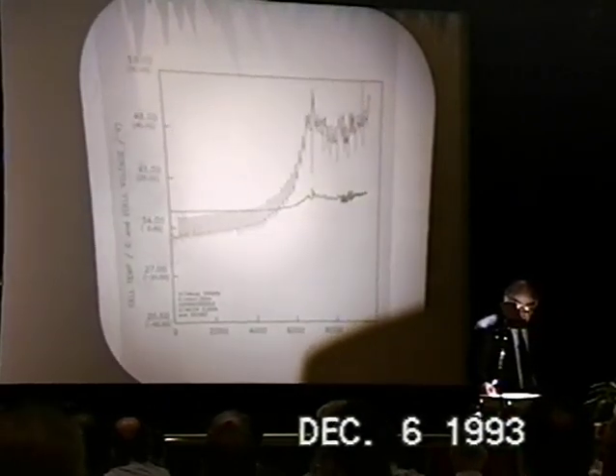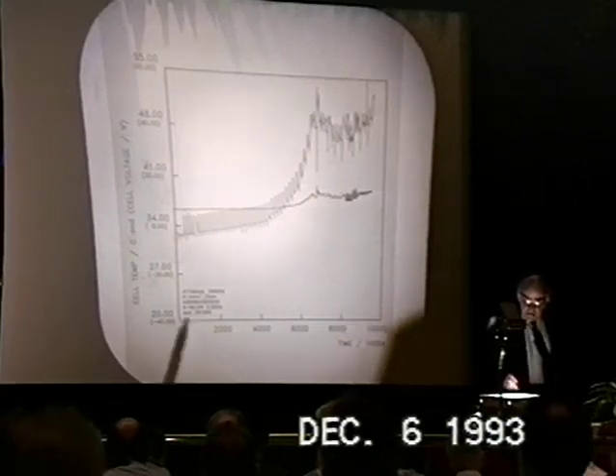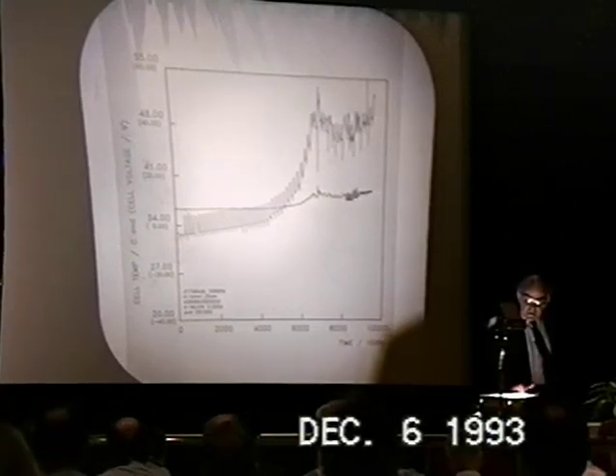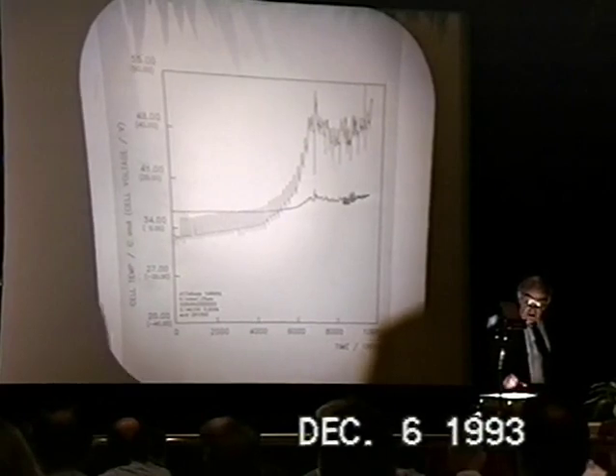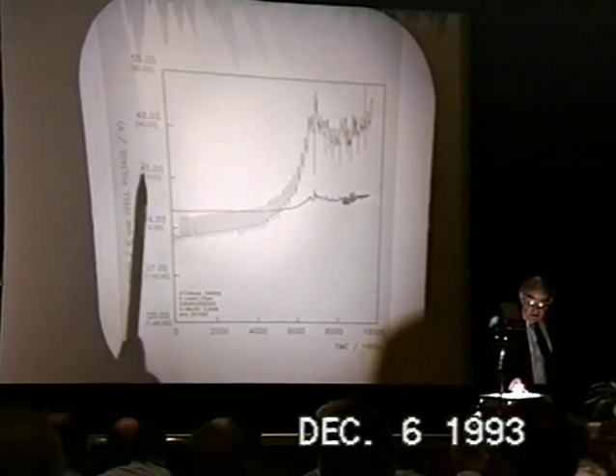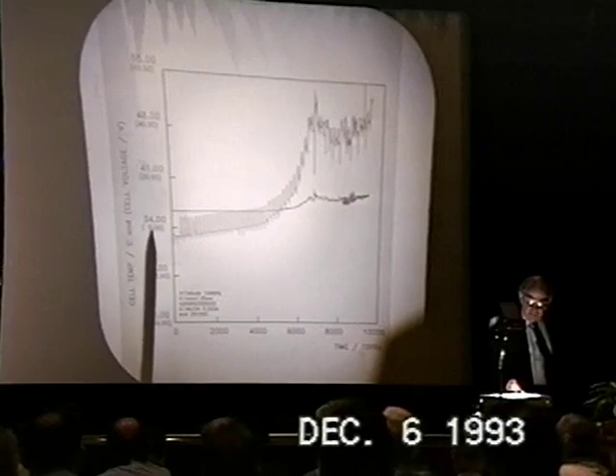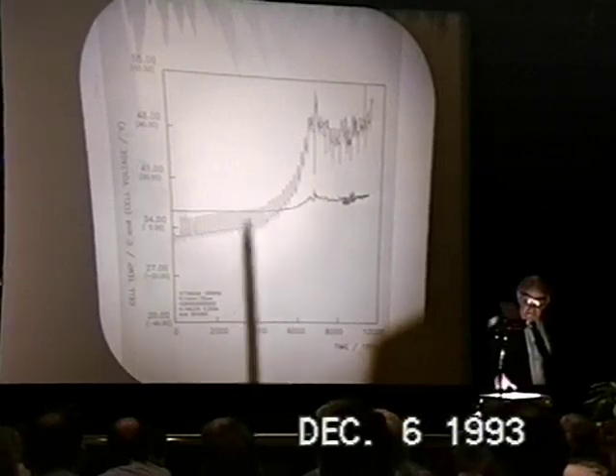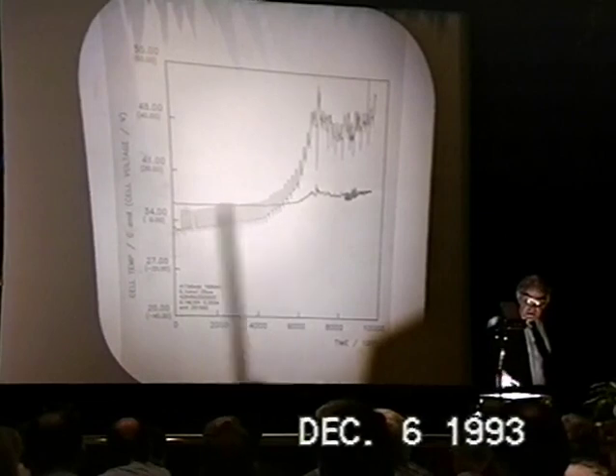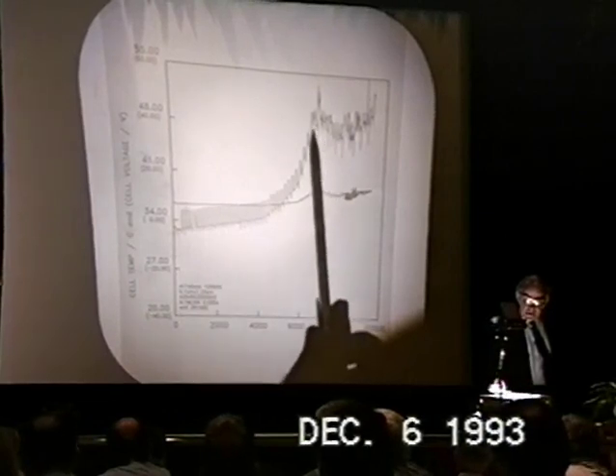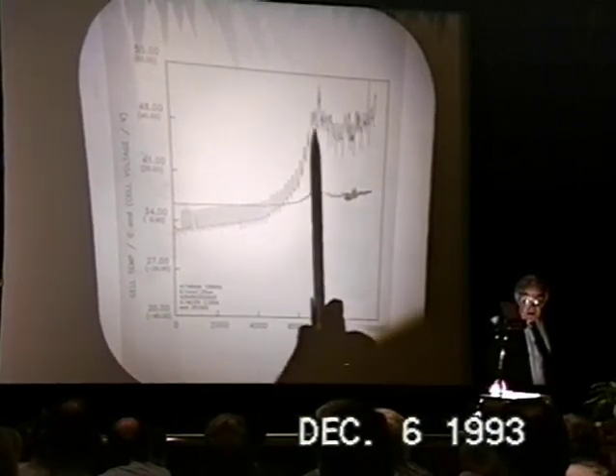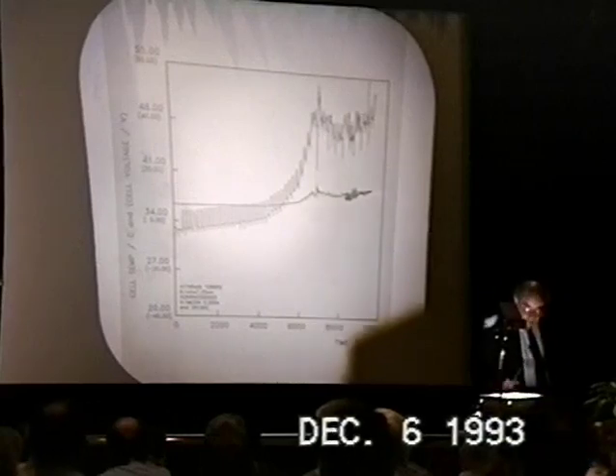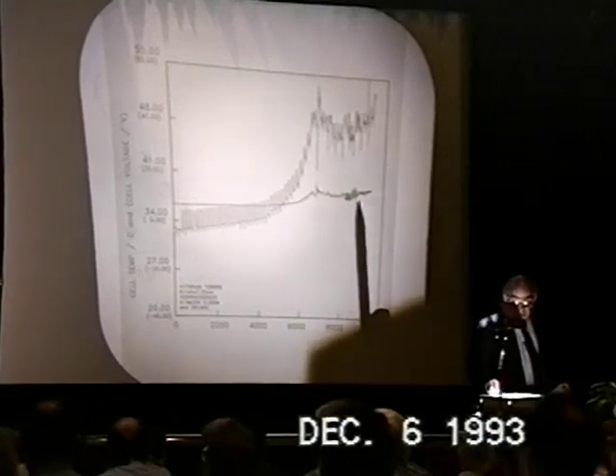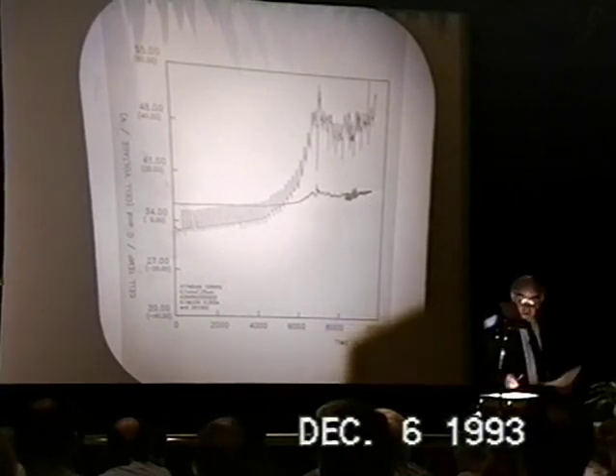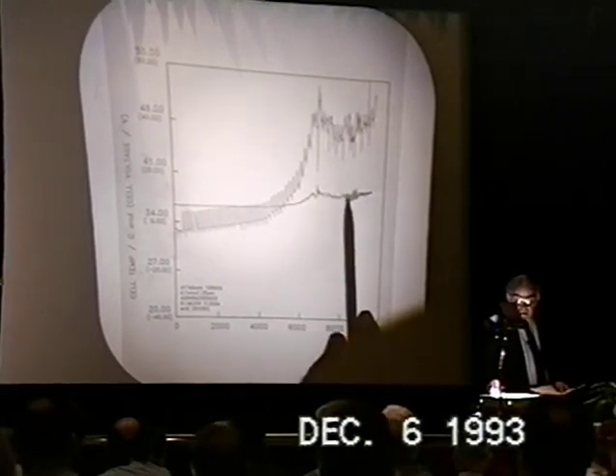If we do an experiment on palladium, this happens to be palladium rhodium, which shows these effects most significantly, and we monitor the cell temperature and the cell potential in parentheses here as a function of time. These are the superimposed calibration pulses. Then we reach a certain temperature at which the system shows either regular or irregular oscillations, in the cell potential as well as the cell temperature.